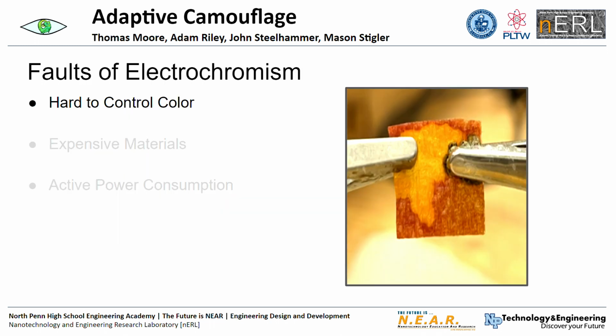After this experiment, we realized that electrochromism is not the way to go for adaptive camouflage for 3 main reasons. 1, the reaction is very difficult to control. As you can see with our turmeric experiments, we were unable to get the paper towel to fully change color. Another reason is the chemicals used are quite expensive and could not be used on a wide scale. Our third reason is the active power supply required for the electrochemical reaction to occur is just not feasible for any one person to use. We believe that there's a better solution.